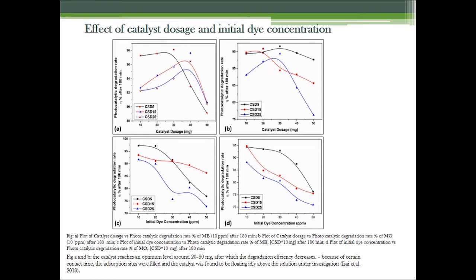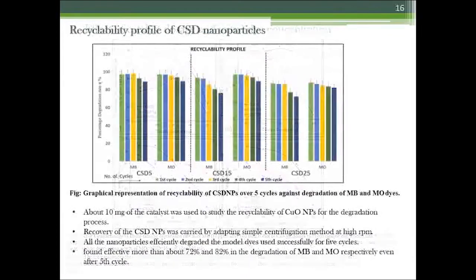So we were curious to know about the recyclability of the nanoparticles once they are used for the treatment of dyes. So we have studied the recyclability profile of nanoparticles. For the practical use of these nanoparticles, it is very essential to perform the recyclability test. Hence, an effort was made to understand the reusability of nanoparticles by using it repeatedly over 5 cycles. You can observe here in the graph the number of cycles. We have used the same catalyst for 5 consecutive cycles for the degradation of dyes. This is for methylene blue and this is for methyl orange.